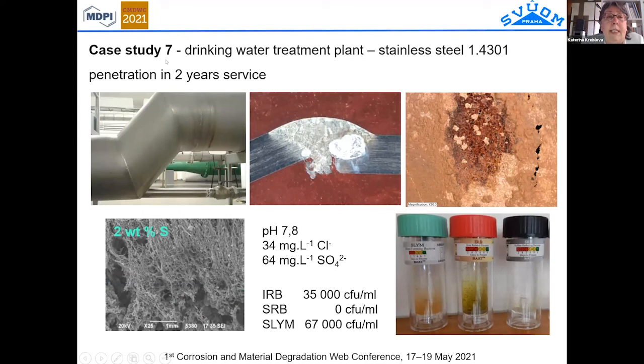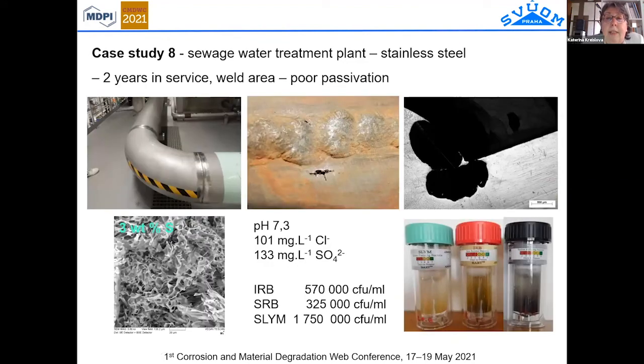Case study 7, also a drinking water treatment plant, again stainless steel. The penetration occurred in 2 years in service, and you can see what the morphology of the surface looks like. The content of sulfur was not so high, but the presence of bacteria, especially iron reducing bacteria, was high. And the last one is case study 8.